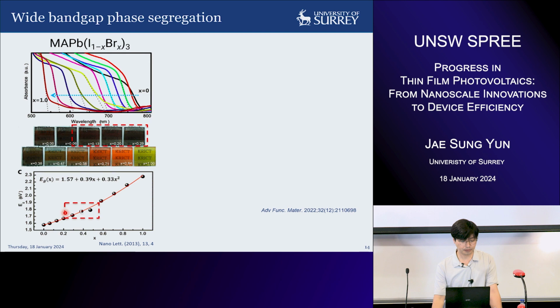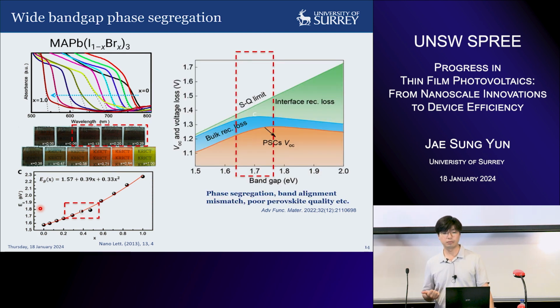So you can see that you can put around 0.2 to 0.5 bromide, and you can tune the band gap around 1.65 to 1.9, where we can have the optimum band gap for tandem perovskites. However, if you put more bromide, which means if you increase your band gap, you will actually have a lot of losses in voltage, and people are reporting that there are maybe interfacial losses in these wide band